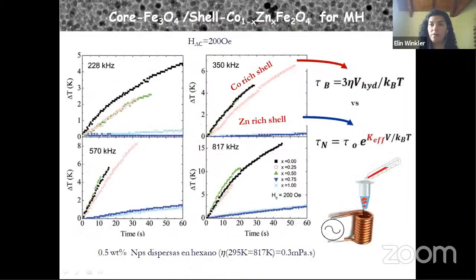So we arrive at the hyperthermia experiment. Remember, we disperse the nanoparticles in the medium. In this case, we disperse 0.5 wt% nanoparticles in a solvent, for example. This solvent has very low viscosity. And we measure at different frequencies, 200 kilohertz, 300, 500, 800, and so on. And we measure the temperature of the medium as a function of the time.